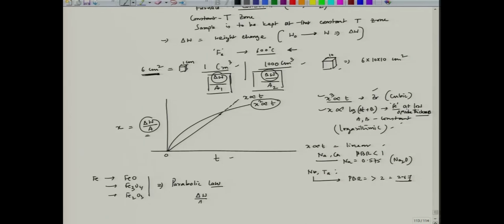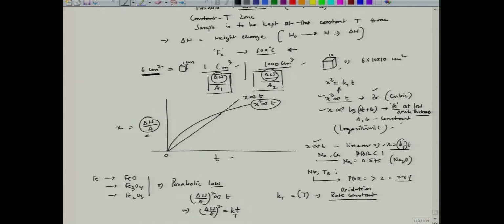So, where del W by A square is proportional to t, I can write it as equal to kT. So, this is at a particular temperature. kT is specific to a temperature, which is a rate constant, the oxidation rate constant. In those cases also, I can write x equal to kT t, which becomes the rate constant for a linear rate law. Here also, I can write x cube equal to kT t, so this is also a rate constant. Here also, instead of proportionality, I can write kT. So, this becomes my logarithmic rate constant, and here it is the parabolic rate constant.